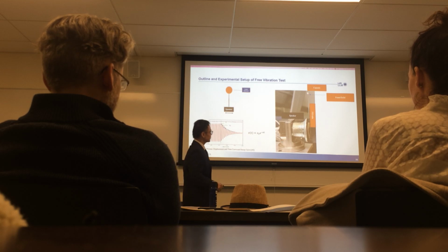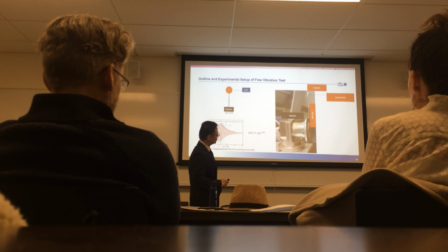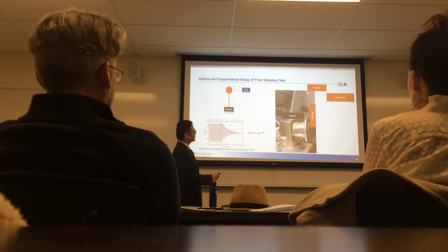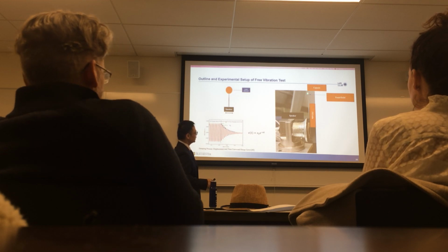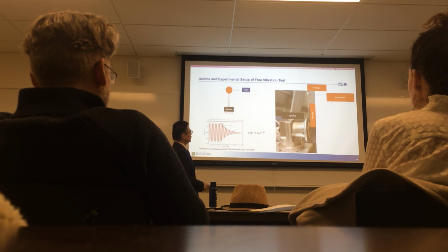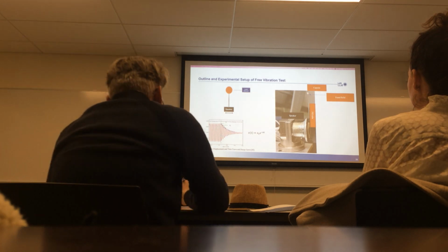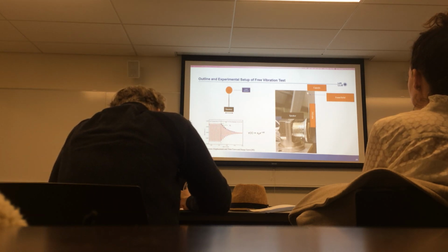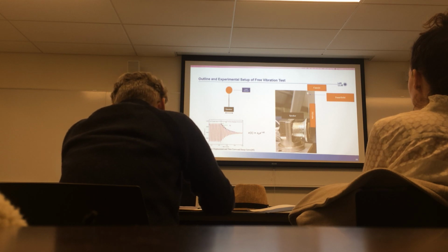So when I start to do the experiment, the target structure will be glued on the speaker. And this is the capsule, and in the dot is our foam structure on the solid structures. And the laser detector will be in this area and will record the displacement and time for this target structure. And from the laser detector, we can get a displacement time curve. And from this time curve, we can get a decay curve. Comparing this damping process and the decay curve, we can measure whether this foam structure dissipates energy or not.